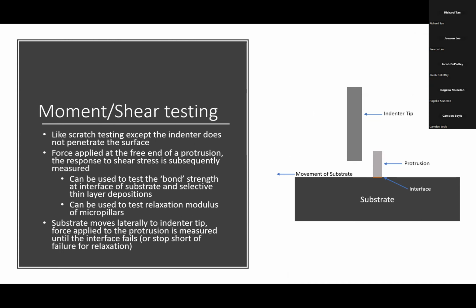This can be useful for testing the bond strength in selective layer depositions at the interface, or for testing the relaxation modulus of different micropillars, like if they're created with PDMS.